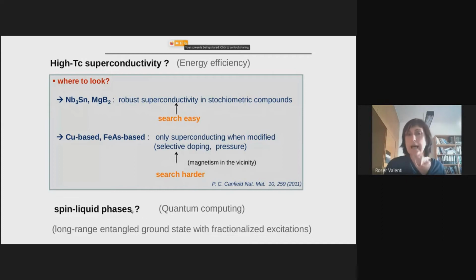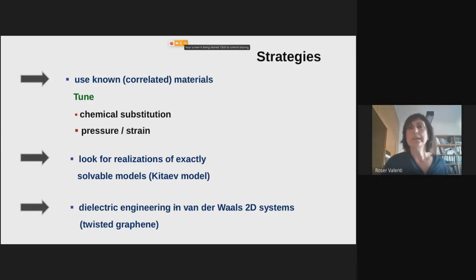So in order to now answer how we proceed in our design, we have three different strategies. So one, and this is more based on these high TC superconductors, is to use known correlated materials and then tune them either chemically or by pressure in order to allow them to manifest other properties. A second strategy is a completely different starting point. We know that there are models in physics, models that maybe have no meaning at all, but we can solve them exactly. And if we can solve them exactly, and with that I mean that we can basically obtain the ground state and excited states, everything in an exact way, then it would be interesting whether we can find a realization of this model in real life. So, look for realizations of exactly solvable models.